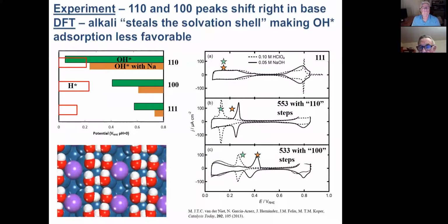So now we recognize that hydroxide is on the surface at low potentials. We can now ask, what does this have to do with the pH behavior? Because what's observed experimentally is that the 111 peaks don't change with pH, but the 110 and the 100 peaks shift to a higher voltage if we go to a basic solution.